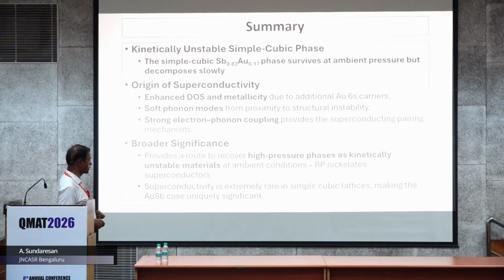These nickelate phases are not stable at ambient conditions. You need to apply pressure and temperature, or just pressure alone, to see the superconductivity. You cannot retain that phase at ambient pressure, so we need to see at what conditions you can retain these phases at ambient conditions.